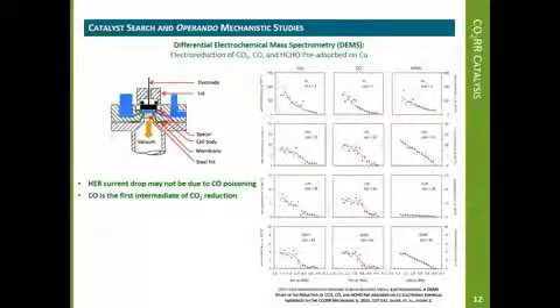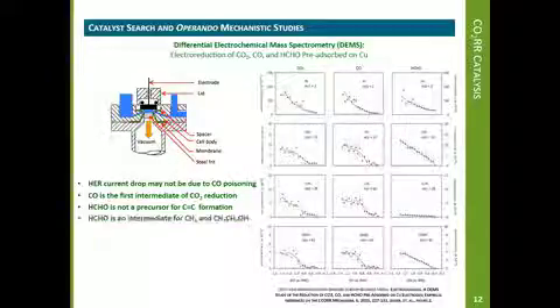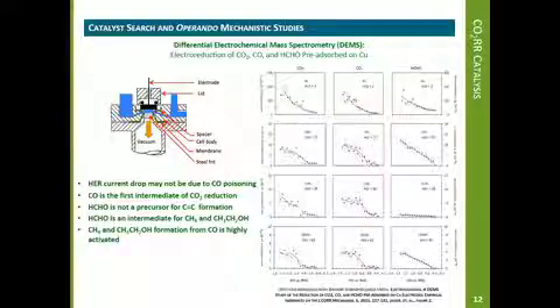CO is the first product of CO2 reduction, as well as the first intermediate in succeeding reactions that include the formation of oxygenated hydrocarbons. The study also reveals that formaldehyde is not a precursor for the formation of carbon-carbon bonds, but is an intermediate for methane and ethanol formation. These two products may be generated from the adsorbed carbon monoxide, but with a higher activation barrier.